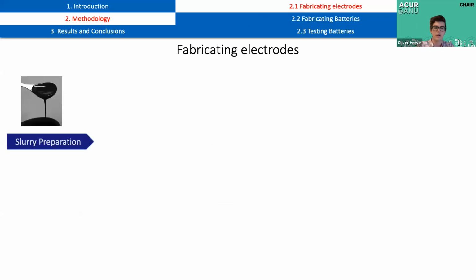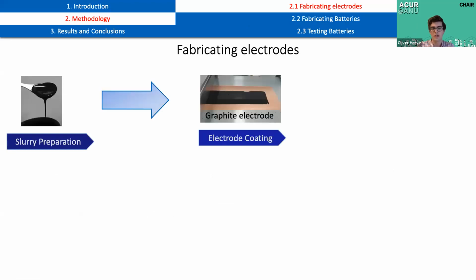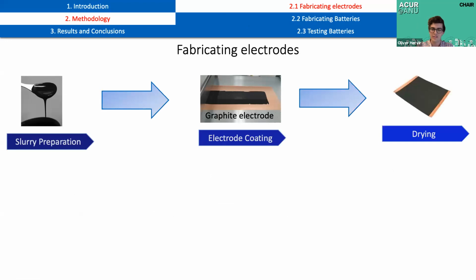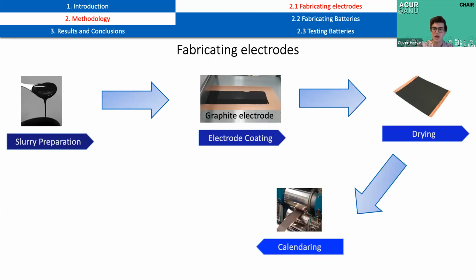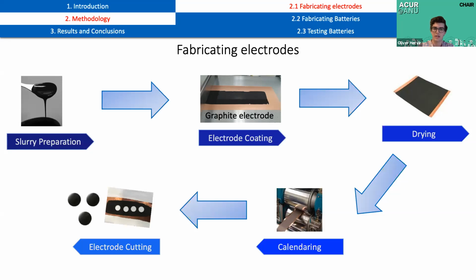So I want to first talk about how electrodes are fabricated, because it's a very critical part of the battery making process, and it took a long time for us to get right. Electrodes are made first as a slurry, where you mix the relevant ingredients in the right proportion. You then coat this slurry onto a piece of foil using a doctor blade, which allows you to achieve a very specific thickness, and you then let it dry. The reason it's important to have a specific thickness is because the density of the electrode can actually impact the way intercalation works, and therefore it's important to get right. We then calendar it, which is another way of ensuring a uniform thickness, and finally punch electrodes out.